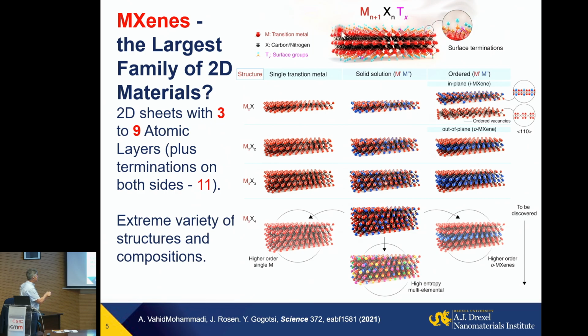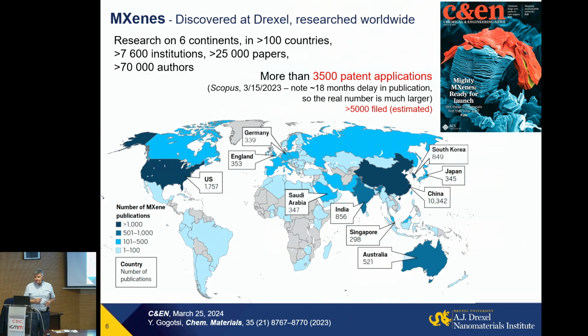And don't forget about Tx, the surface terminations. What is also very important, if you take graphene and modify its surface, making graphene oxide with oxygen hydroxyl groups, or graphene covered with hydrogen, you kill the conductivity. It drops by 6-7 orders of magnitude. In this case, you can change surface chemistry and still keep the material conducting, because the transition metal elements are there, and they will provide conductivity. For some of the MXenes, especially thinner layers, you can open the band gap, for example, by putting oxygen on the surface and pulling 2 electrons from each atom here. But for many of them, you can maintain conductivity. Naturally, with this huge number of materials, there is research going on all over the world.